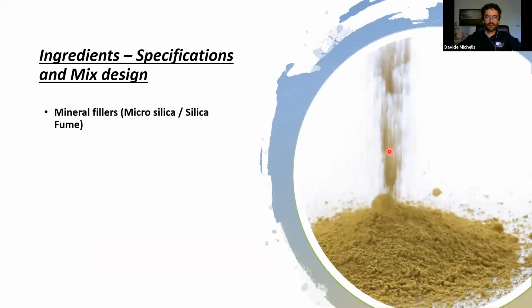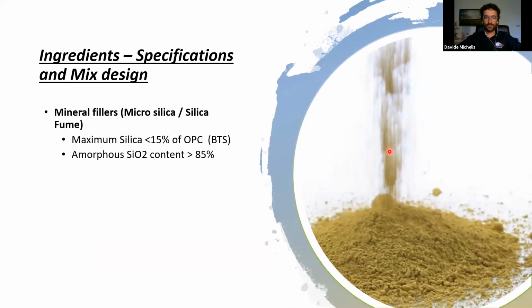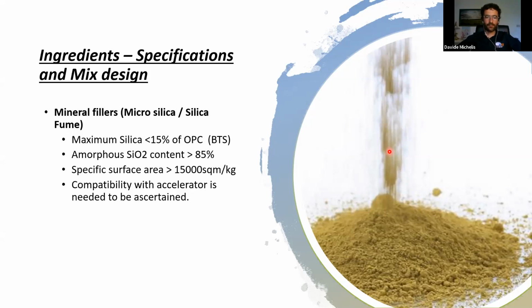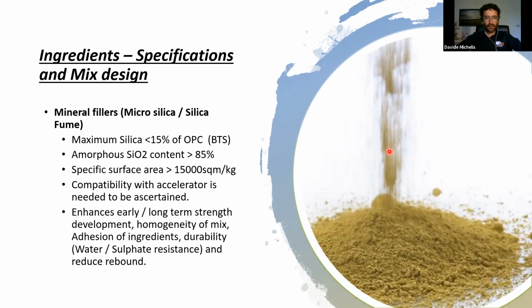There are also some mineral fillers, as additional ingredients. As a rule, we should not exceed 15% of the OPC, and this should have an amorphous silica content higher than 85%, and a very high specific surface in order to be kept inside the mix design in a proper way without any bleeding problems. Of course, the compatibility with the accelerator must be checked before any qualification process. What's the aim of putting mineral fillers? As we said already before, it's to enhance the early and long-term strength and durability. And of course, it enhances the adhesion of the mix design during the spraying sequence.